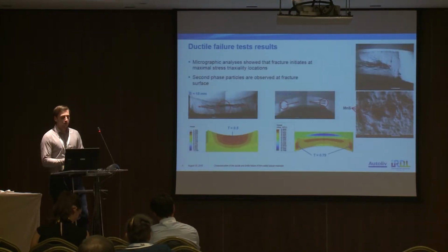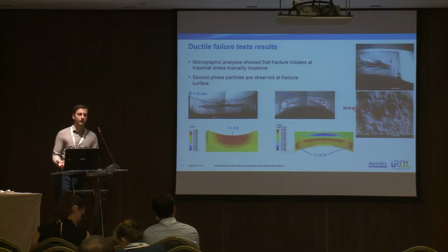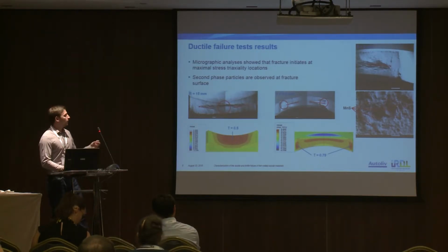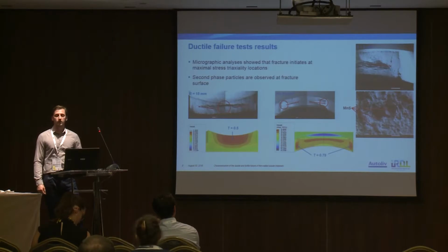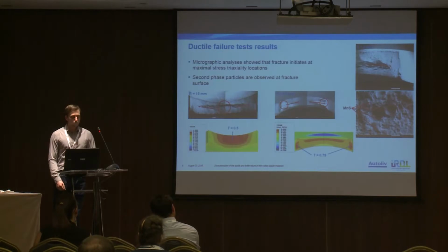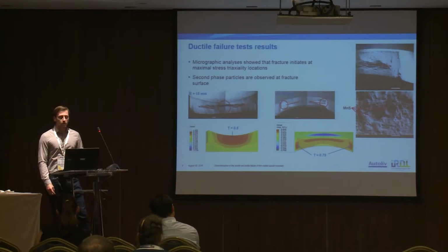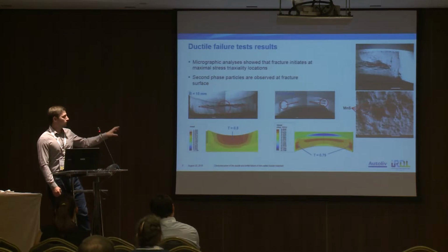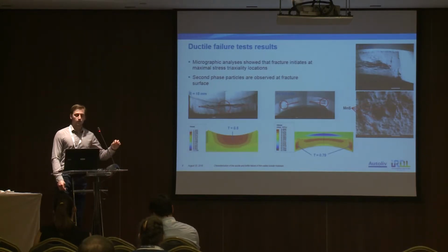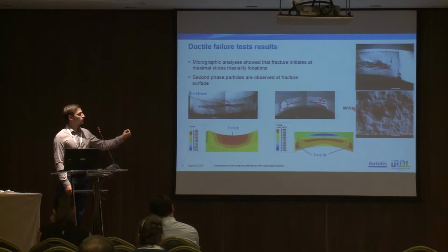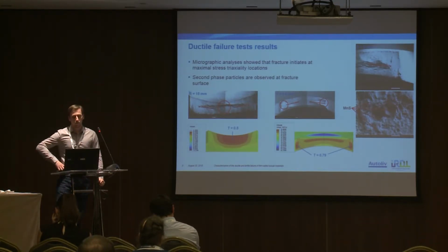So, with this test, of course, as there is a pop-in phenomenon, we have to check if the fracture surfaces are purely ductile or if there is any cleavage on them. Sorry, micrographic analysis showed that there is only ductile fracture surface, with the presence of two-sized dimples. This is due to the damage mechanism of our material.